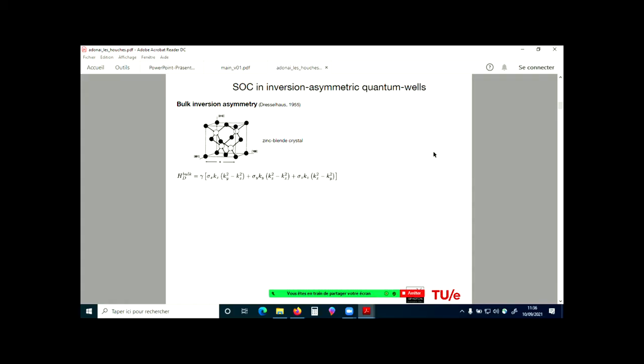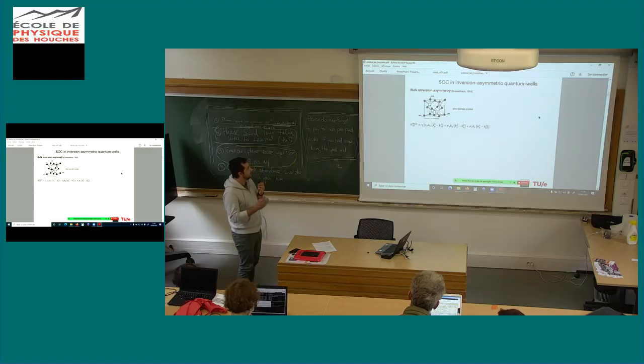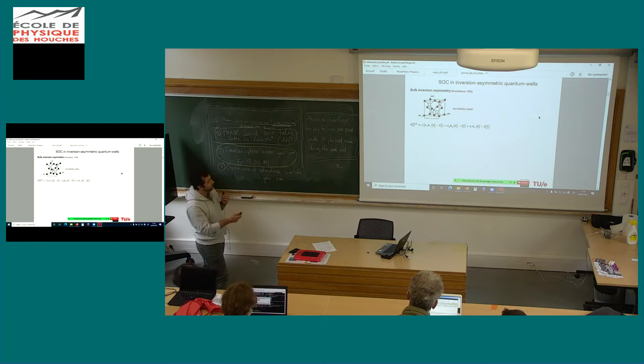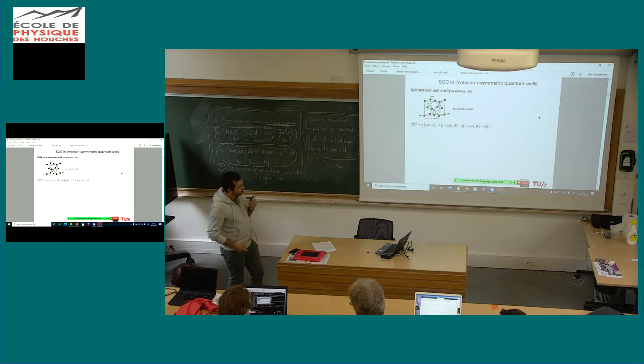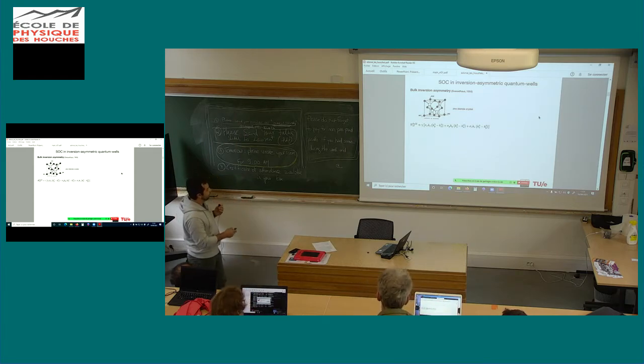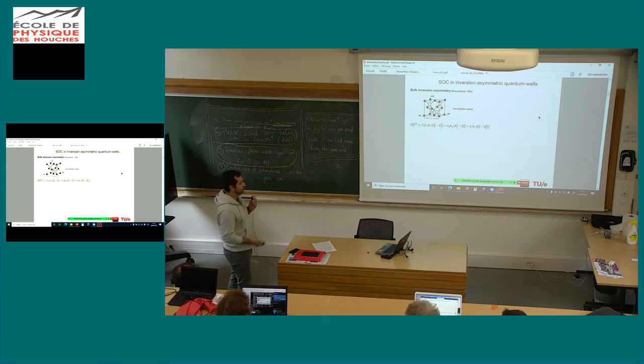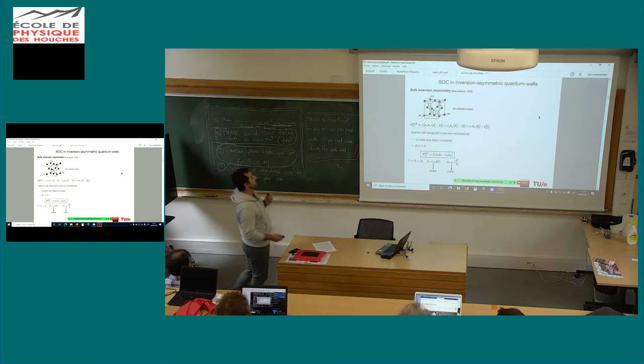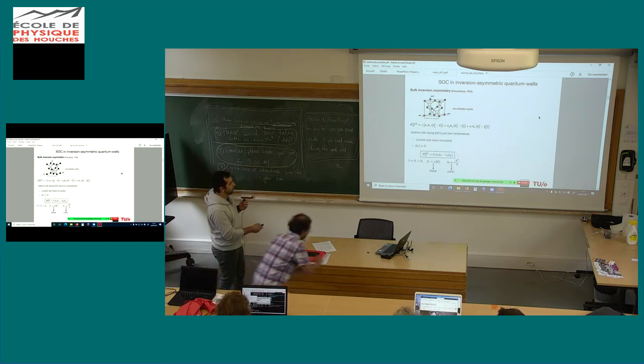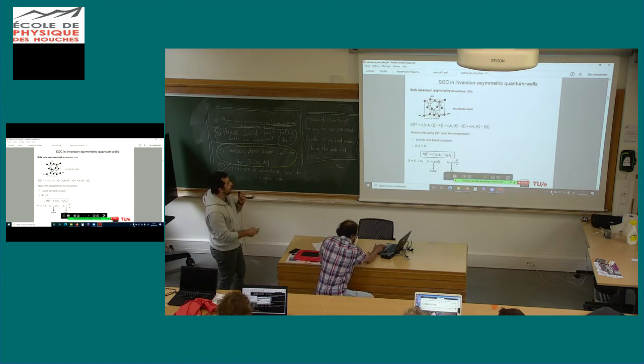I'll present a very simplistic model, but a semi-analytical one for the problem. I'm looking at quantum wells with spin-orbit coupling and inversion asymmetry. There are two important ingredients in this kind of system. In a zinc blende crystal, we lack the inversion center, which gives rise in bulk to the so-called Dresselhaus spin-orbit coupling. These are the expressions for bulk. But if we apply confinement to a quantum well along the crystallographic 001 direction, and assume low temperature, we can simplify our problem.